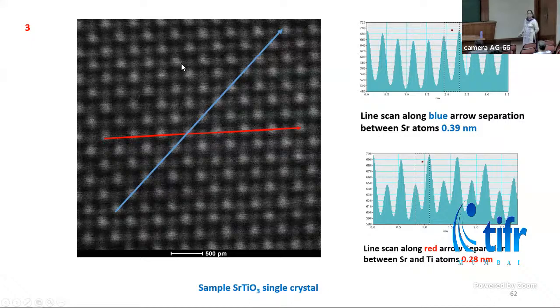As I mentioned earlier, from TEM we can get information at atomic scale. So this is the strontium titanate single crystal. Here we can see the bright atoms. These are single atom columns. The bright atoms are strontium and the gray atoms are titanium.